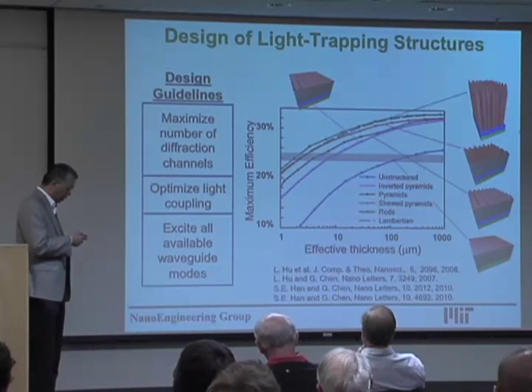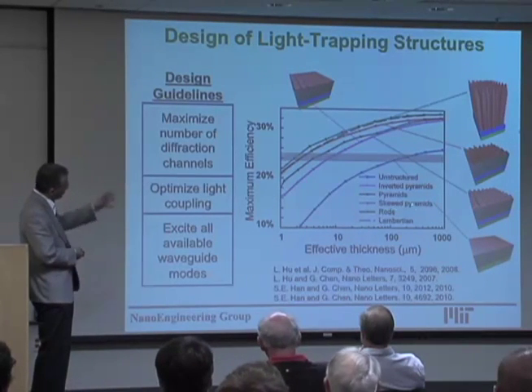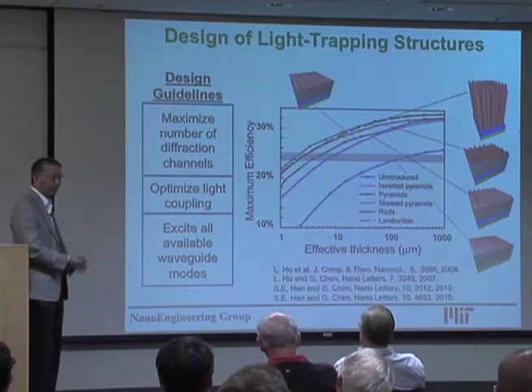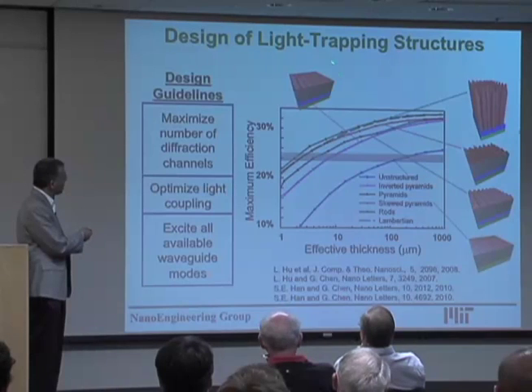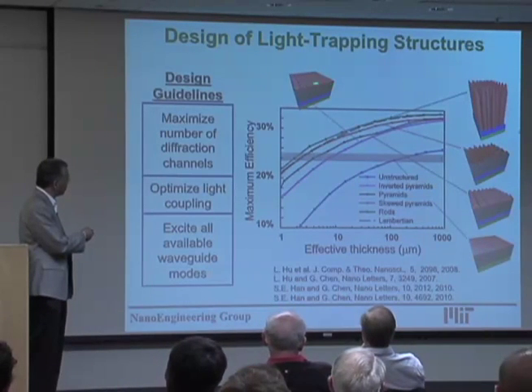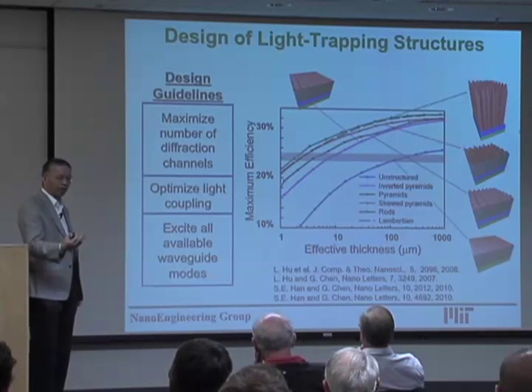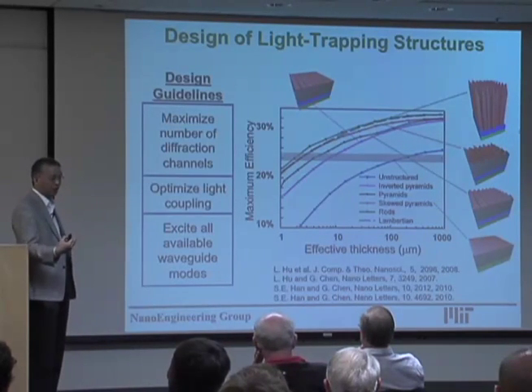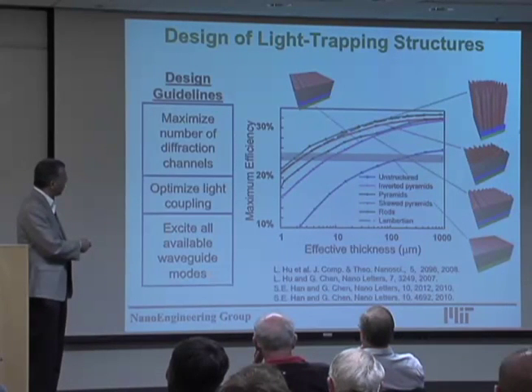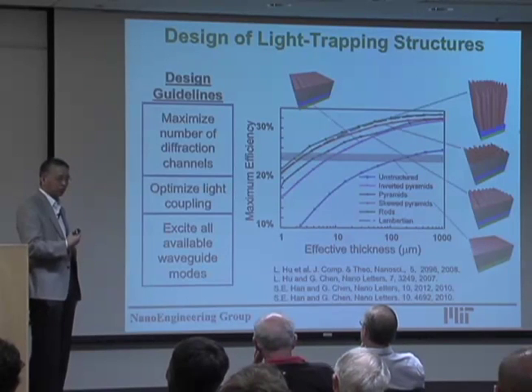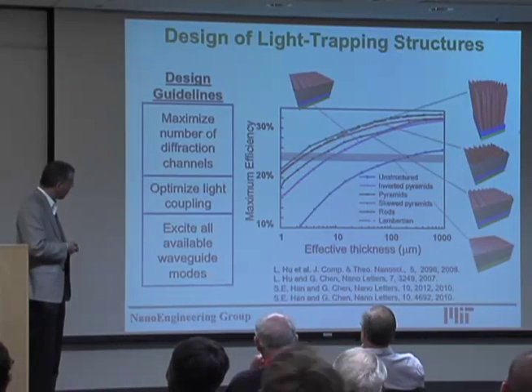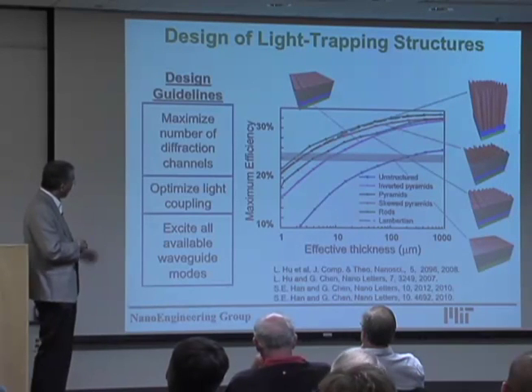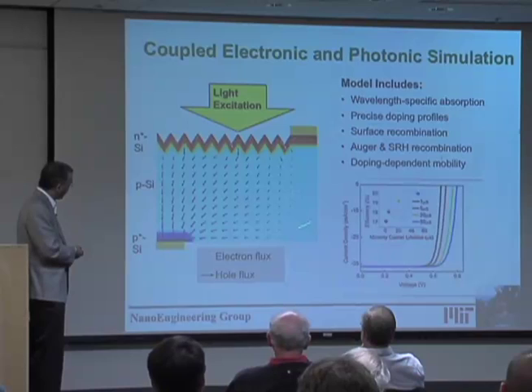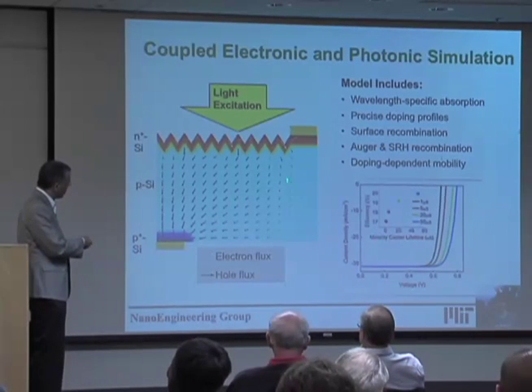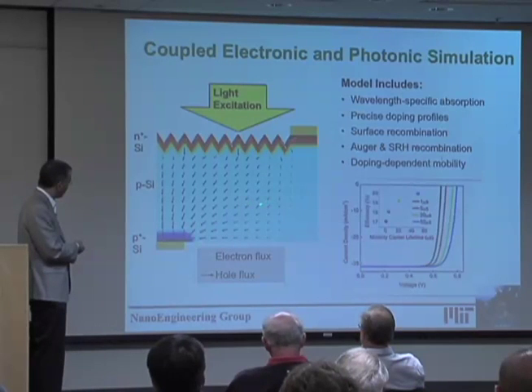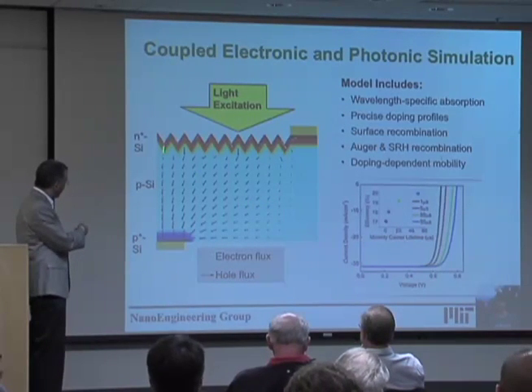With that as motivation, we asked, among all of this, what would be the easiest to fabricate? And this is the silicon thin film with the inverted pyramid, because we know you can etch it easily with chemical etch. Also, this has a much smaller surface area increase, which is beneficial for efficiency. So that's an optical design, and then we did some electrical simulation. This is a device simulation, with the drift diffusion equation, contacts, and light absorption.